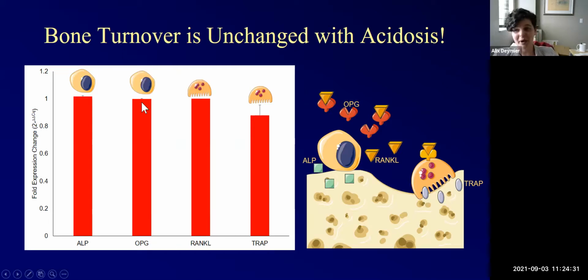You can see they're about equal to 1. So that doesn't seem to be causing any changes. And here, these two are associated with bone removal. And even then, there's no significant difference compared to controls. Now, these were taken at day 14. And I'm thinking, man, I have all these changes to my bone, and yet it's telling me that nothing has changed in my cellular activity. That seems really, really fishy.